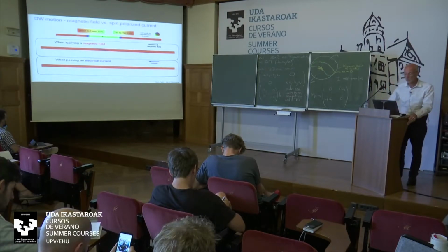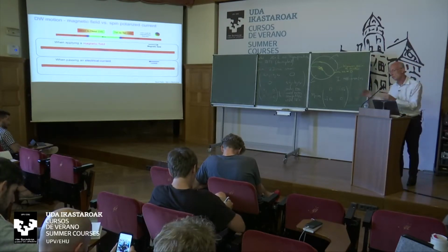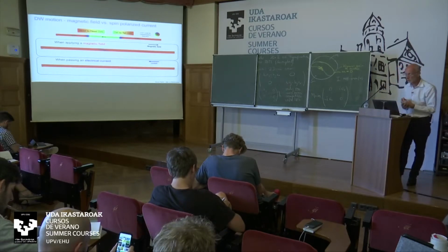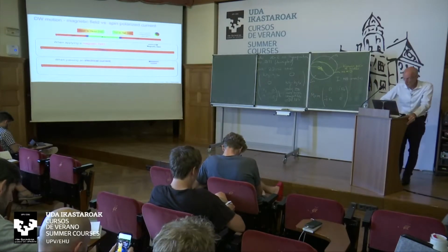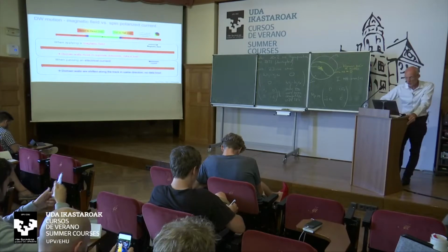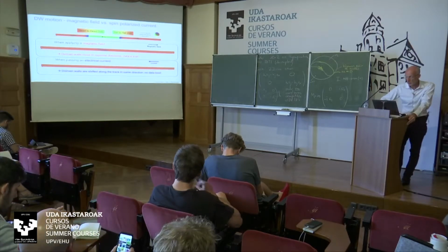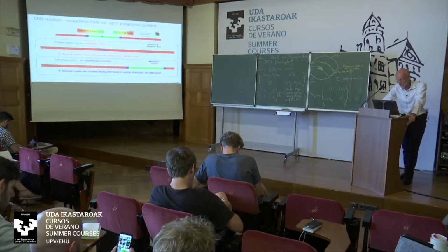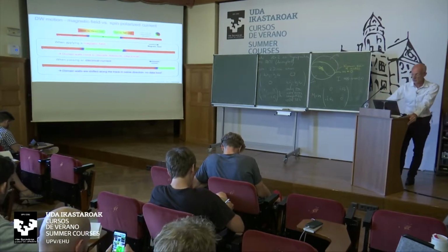Using currents, we can move a series of domain walls in the same direction, and by reversing the current direction, we can move them in the opposite direction. This was a proposal that NIST made a few years ago, and we were able to demonstrate that this actually works. And in simple, soft magnetic metals, you can shift the domain walls in this way at speeds of up to about 100 meters per second.